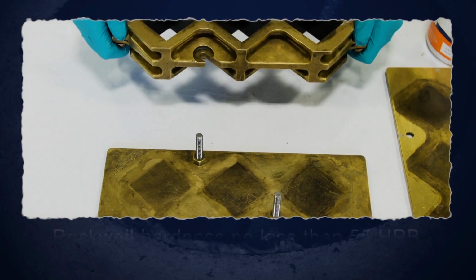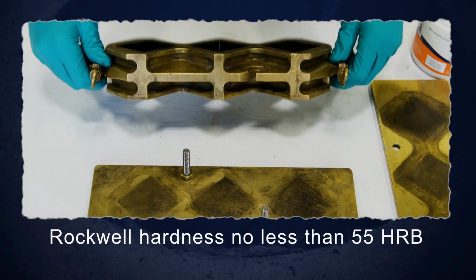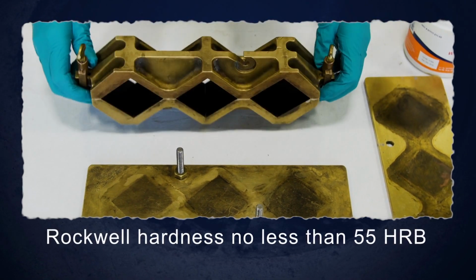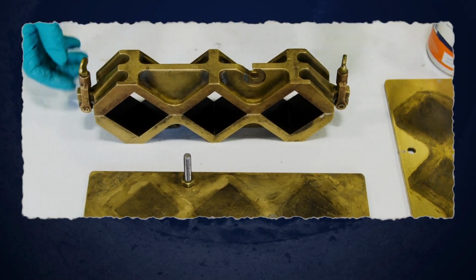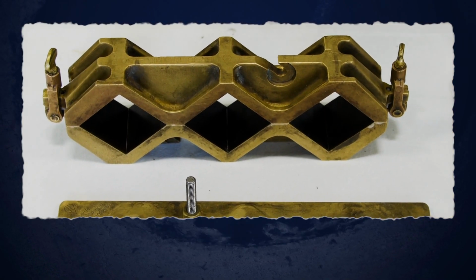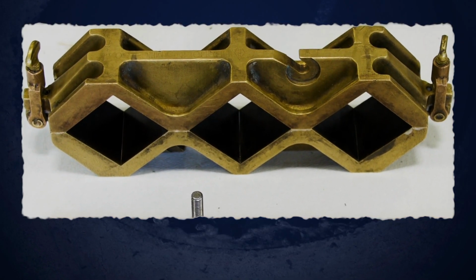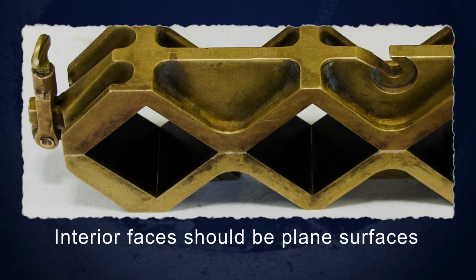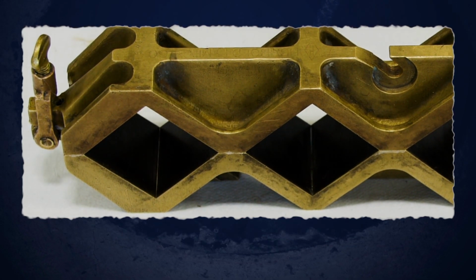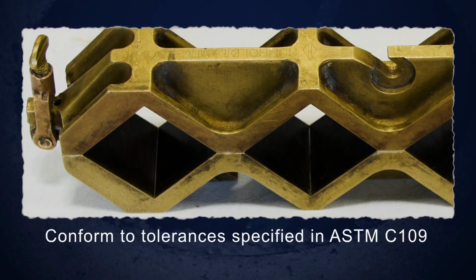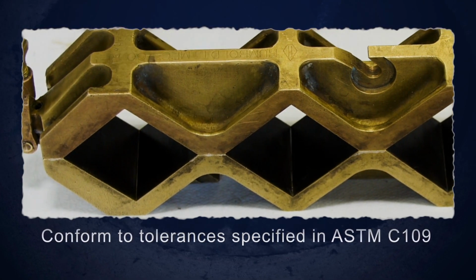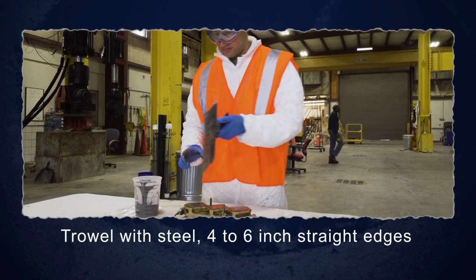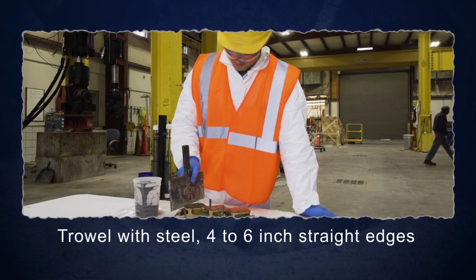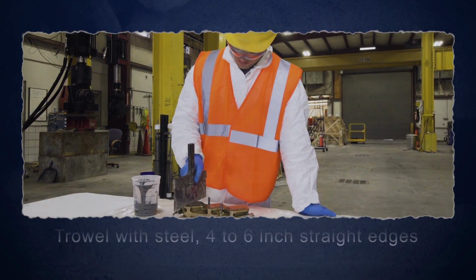For new molds, the Rockwell hardness number of the metal should be no less than 55 HRB. The sides of the mold should be sufficiently rigid to prevent spreading and warping. The interior faces of the mold should be plain surfaces and conform to the tolerances specified in ASTM C109. A trowel is needed, having a steel blade 4 to 6 inches in length with straight edges.